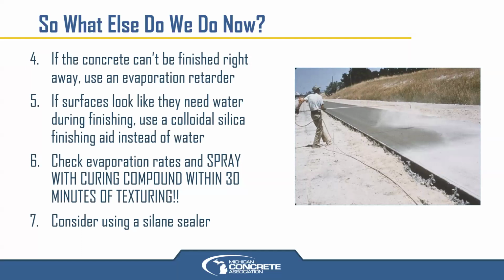So curing compound is the cheapest insurance that you can use, because it's going to protect that surface when it's most critical, early ages, and give you the best chance for a durable surface. In addition to that, you could consider using a silane sealer. A lot of agencies we see using that, especially near the late fall, prior to our freeze thaw cycles starting and potential for salt being applied to very young, green, or freshly placed concrete, to try to protect it, especially in the first winter or two. But it's a good idea for any concrete. If you want to protect your investment, it's another step from curing compound.